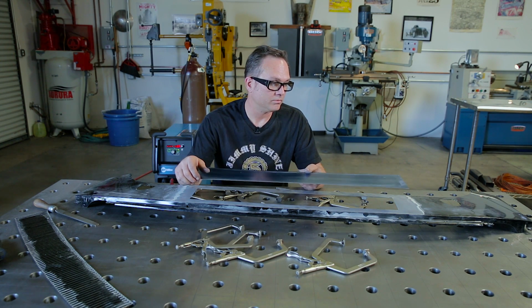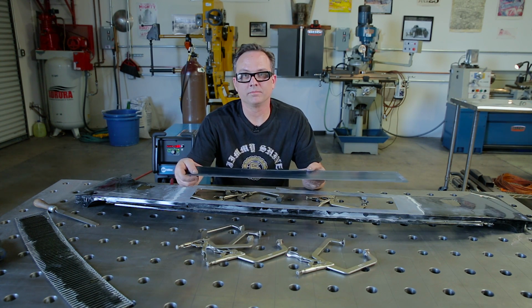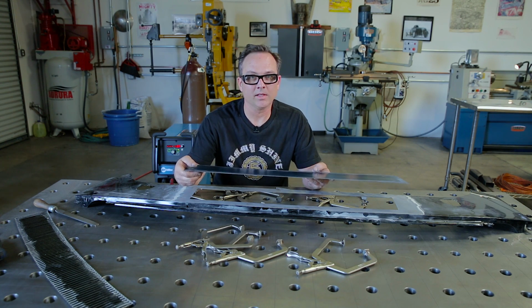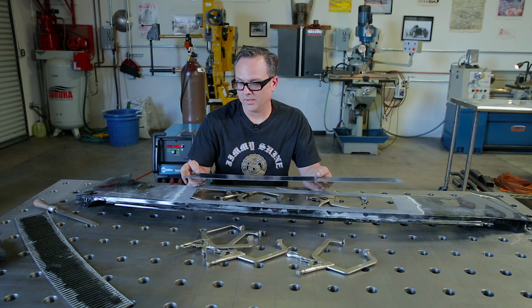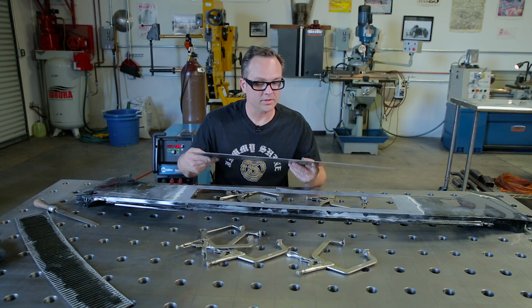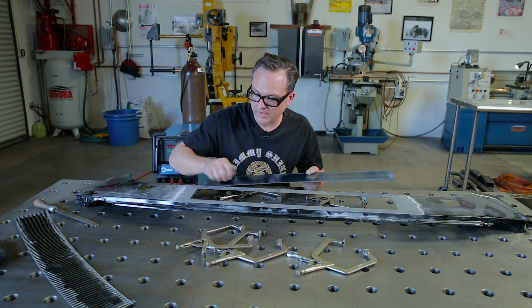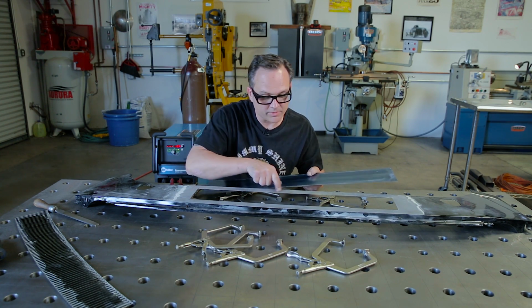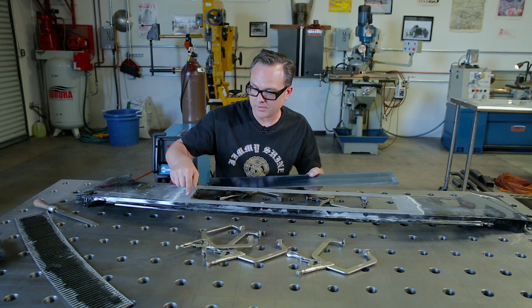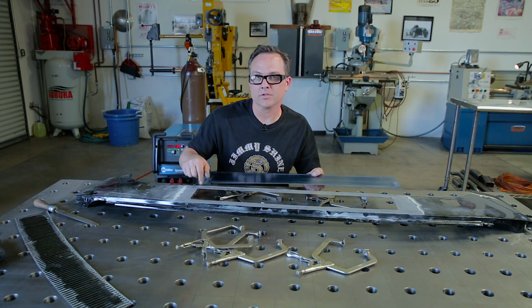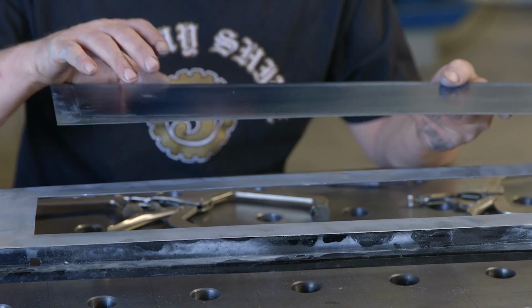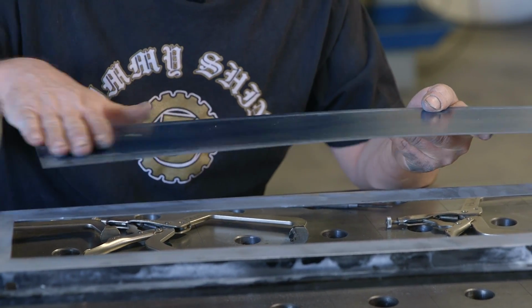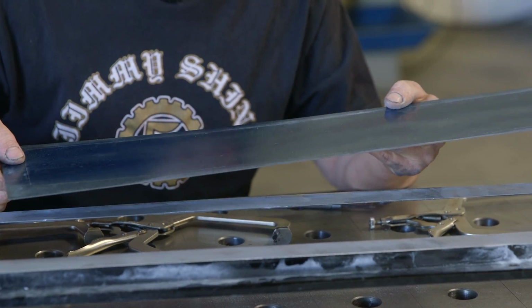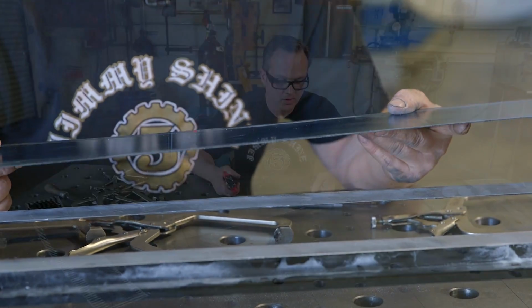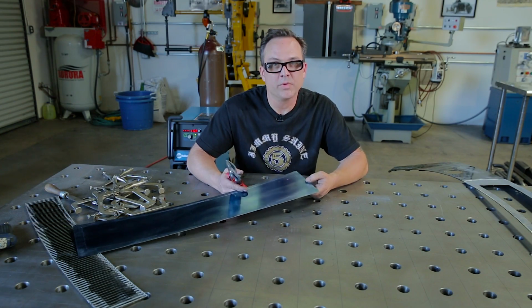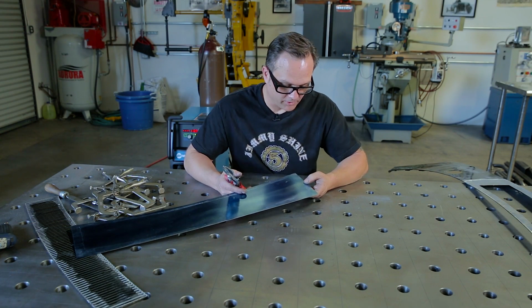I always thought welding was about 10% welding technique and 90% fit and preparation. And as you can see, after I filed it, I even went back and there was some more paint residue, so I took a DA sander and cleaned more paint residue off. And even this, after we cut it out, I'll clean that layout fluid back off because that can also contaminate our weld. So now we have our new piece that we're using as our filler panel.